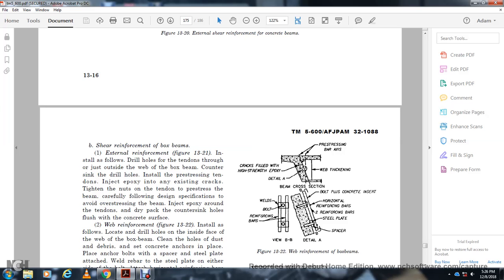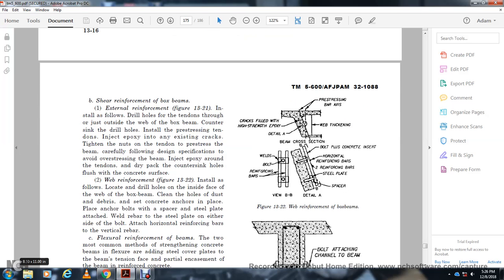box beam with the countersink and a drill hole to install the stressing tendons. Inject epoxy into any existing cracks. Tighten the nuts on the tendon to prestress the beam, carefully following the design specification to avoid overstressing the beam. Inject the epoxy around the tendons. Dry-pack the countersink hole flush with the concrete surface.